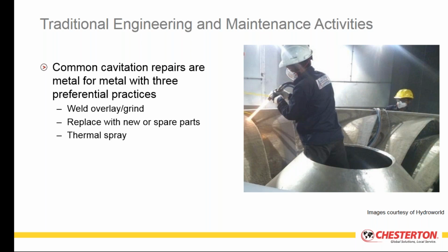Thermal spraying has become more and more common. It's basically a high velocity oxygen fuel derived method, where you are passing a metal powder or a rod under high velocity airflow into a high velocity airstream. As it passes through an arc, that metal rod, wire, or powder is liquefied in that arc flame and is then thrust and forced upon the surface, where it coalesces on the surface as a hard metal.